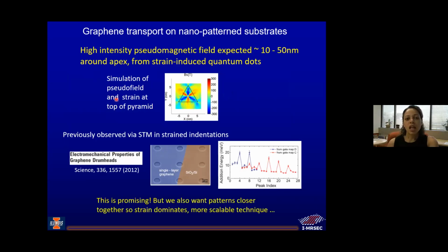Okay, so this was really useful and interesting, but it wasn't quite as clear as we had hoped. And one of the reasons for this is that the patterns were relatively far apart. If you looked at these patterns of nanopillars, they're spaced by, I don't know, 300 nanometers or something. That's just because of the way we did lithography. It was really hard to get closer features at first. Okay, so it's promising, but we wanted patterns that were closer together so that the strain dominated, and maybe even have a more scalable technique than having to individually pattern every pillar.